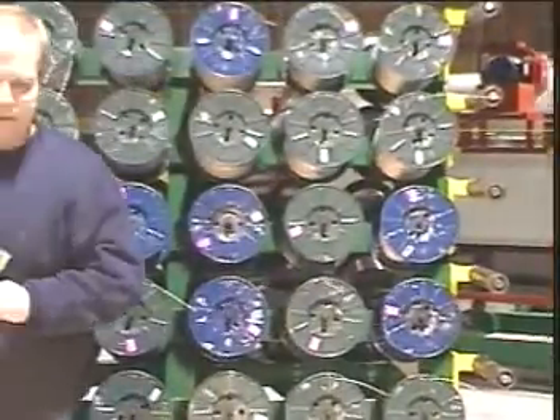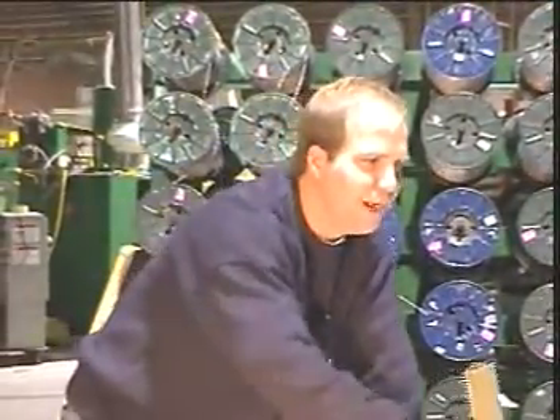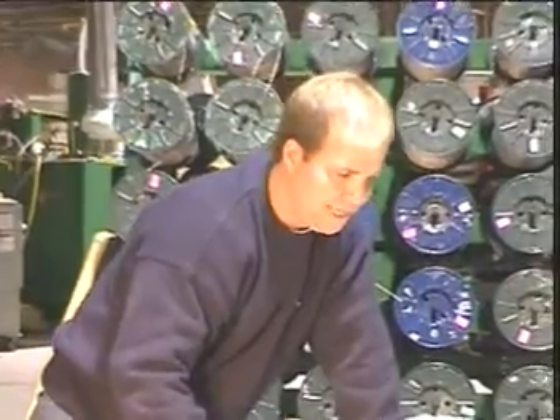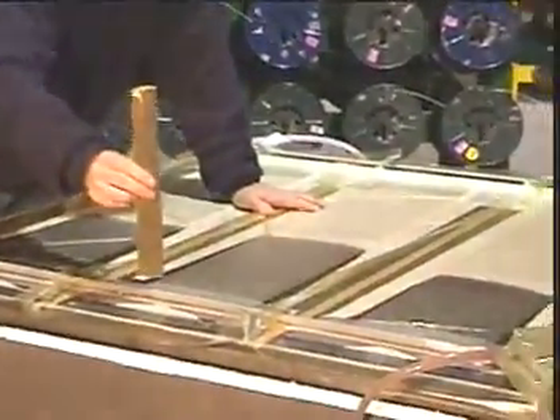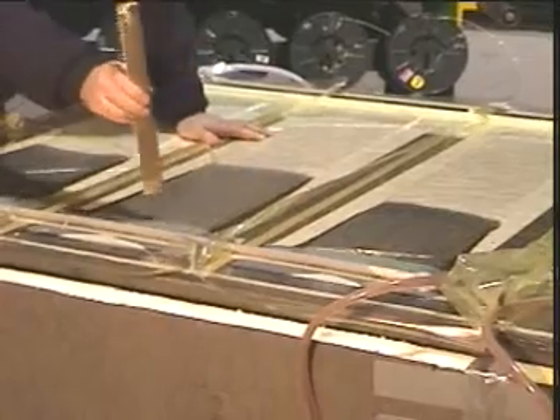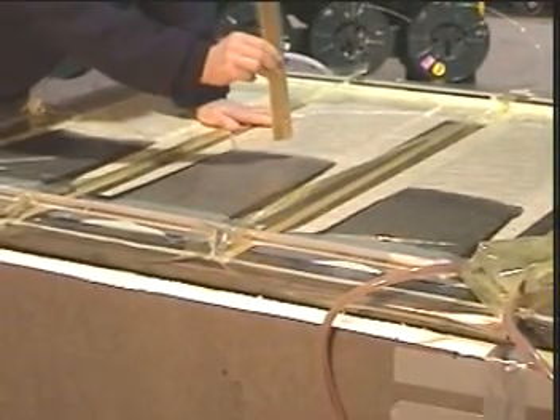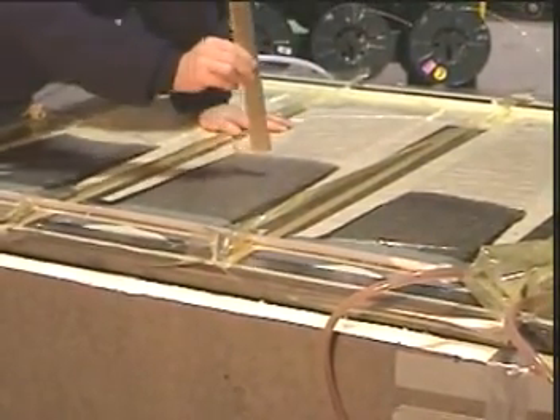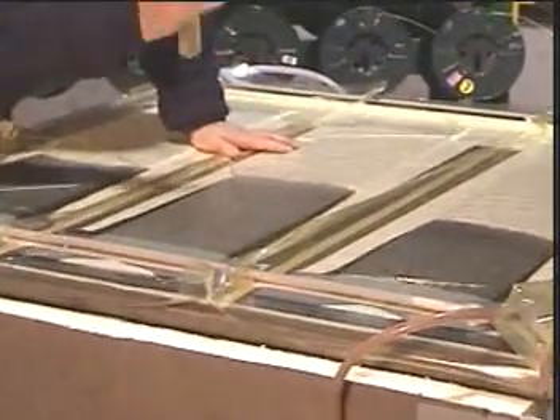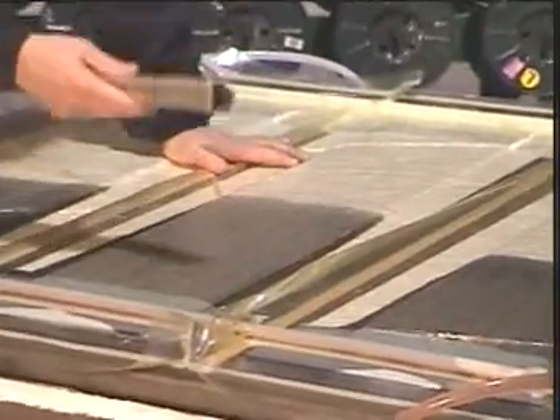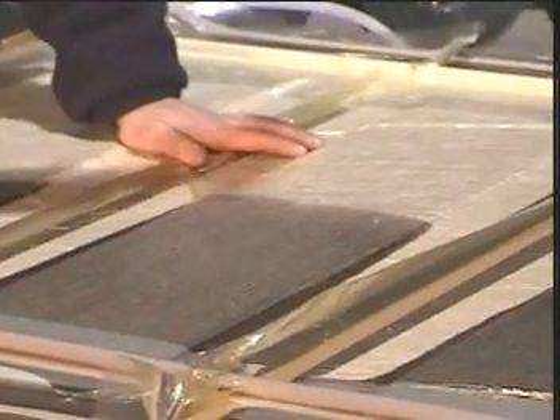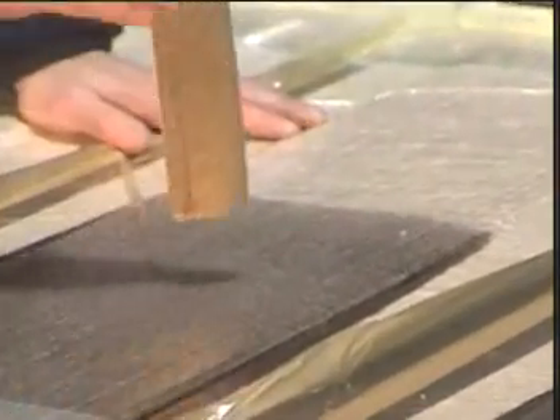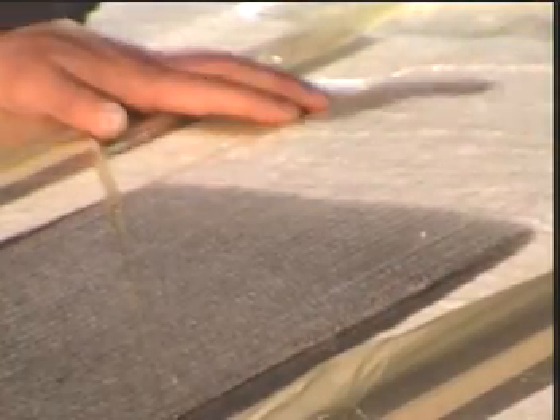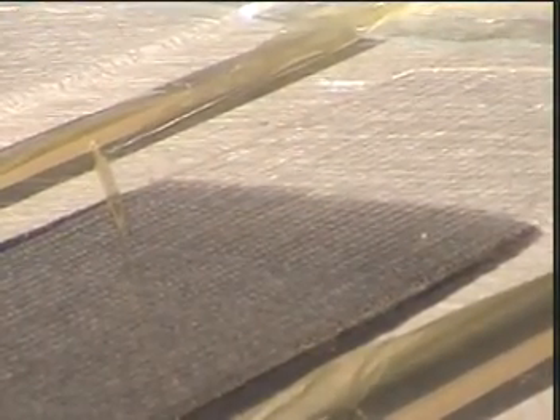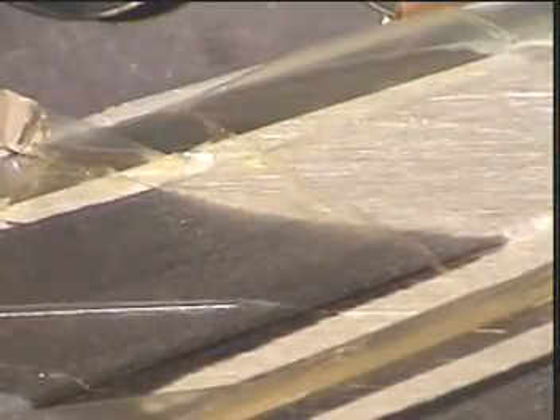Back here in the Hardwire panels, you can just see a nice, even progression of the resin moving all by itself. What's important here is the resin is moving in a straight flow front. It's basically wetting out from the inside out, and what that means is as it moves very carefully and across, you'll have a very uniform flow front. Things can't really go wrong because you're not trying to dump resin over the top of the panel. You're moving it along the panel and through the thickness as you go. You can see the Hardwire now showing up from underneath the glass.